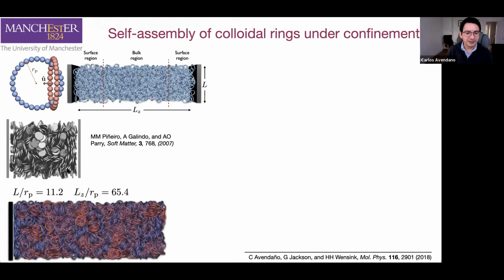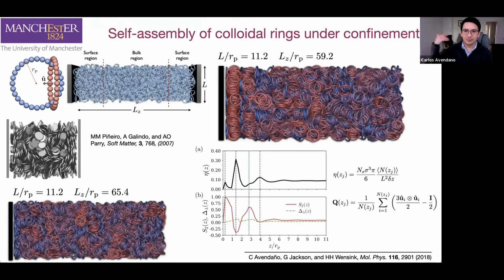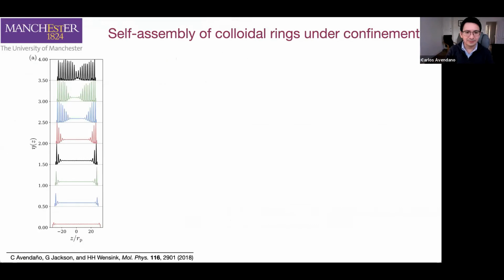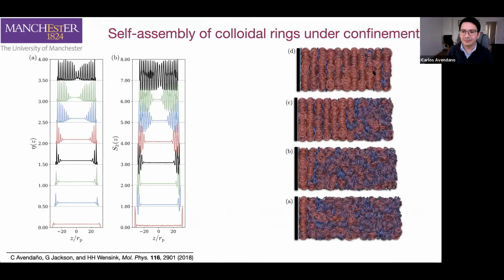What we observed is that as soon as we place the particles and we increase the density, we start observing the formation of these layers, similar to the simulation that I showed you before in bulk. And if we keep increasing the density in the system, they tend to form the same smectic phase that I showed you before. But the particles are not lying flat with respect to the surface. They are completely lying perpendicular.